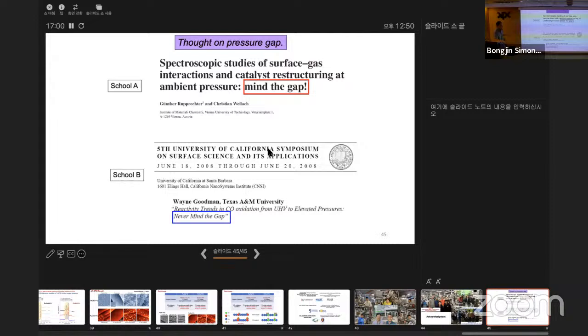There are many other reasons, but we start seeing this at about 100 millitorr, a little bit of pressure where it's going from molecular flow to viscous flow. That region is about 100 millitorr, about the millitorr region. Then you start to see a lot of these unexpected things, and that might explain some of this in pressure gap science. But again, there are a lot of other approaches.